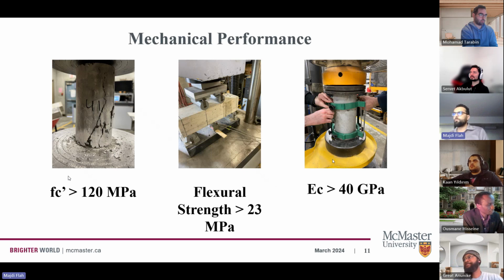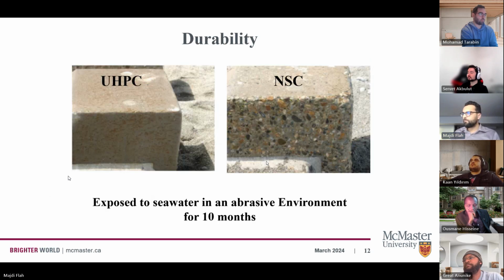So for the mechanical performance, there is an agreement that the compressive strength has to be more than 120 MPa. The flexural strength is more than 23 MPa, and the modulus of elasticity of concrete, according to the literature review studies I've reviewed, is always more than 40 gigapascal.